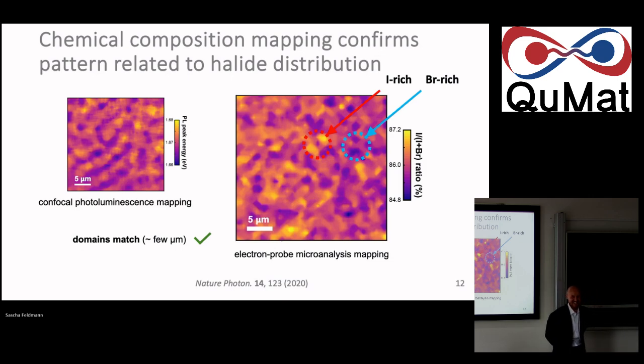Iodide-rich spots have a somewhat lower band gap and they accumulate more excitons, and that's why you see high luminescence. Also, except for the spectral shift, you see high luminescence. Yes, so the intensity would also be correlated with that, exactly. I'm not showing here some nice drift-diffusion recombination modeling that you can do to quantitatively capture the intensity mapping, yes.